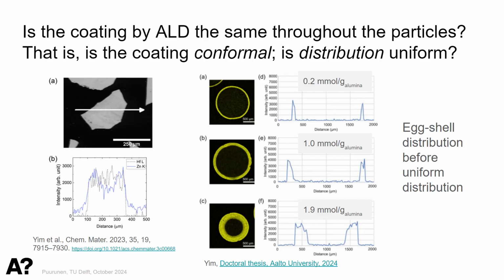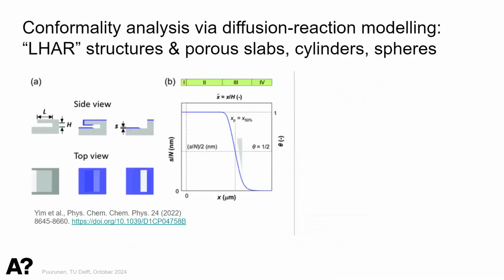These had 1 millimeter as their size, so they are pretty big, and they are spherical, and clearly the higher the dose we deliver, the deeper the film is growing, and it's easy to imagine this actually. So in addition to the targeted uniform distribution, it's very clear that we can also make eggshell catalysts this way. Whether it's useful, I don't know, but that's how ALD progresses. These have not been published elsewhere yet, and are in Ji-Hong-Yim's doctoral thesis.